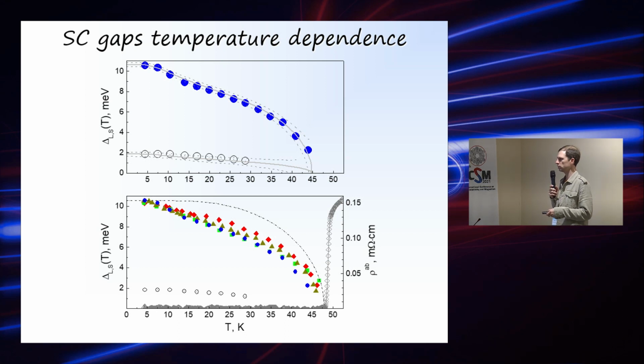And the resulting data, you could see some statistics on the large gap temperature dependence, but for the small gap, as I said, it's only one. And here is the BCS temperature dependence, and you could see that the critical temperature is the same as in the bulk resistivity temperature dependence.